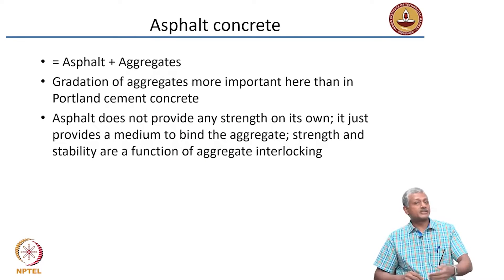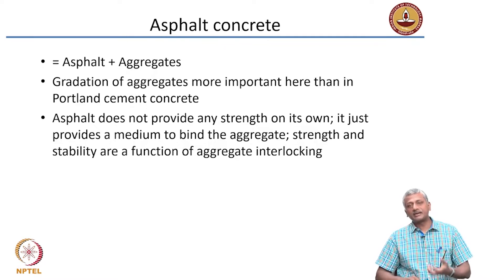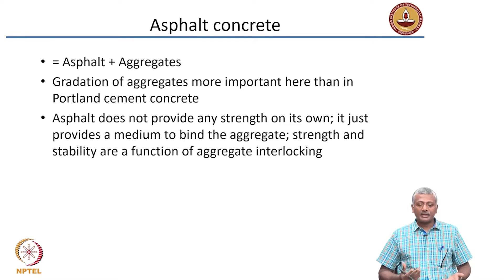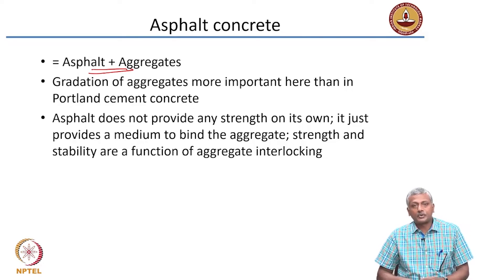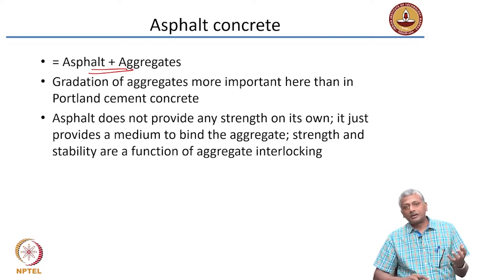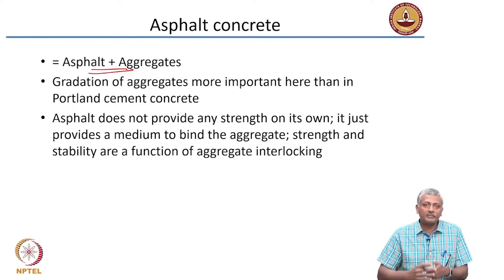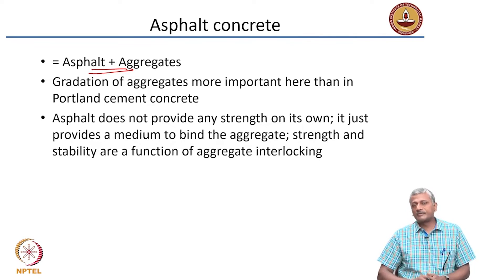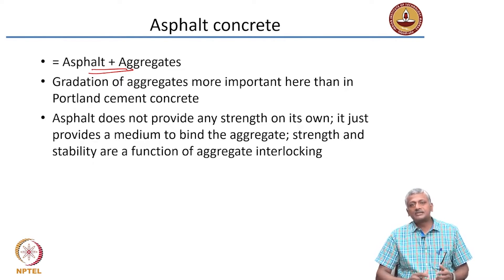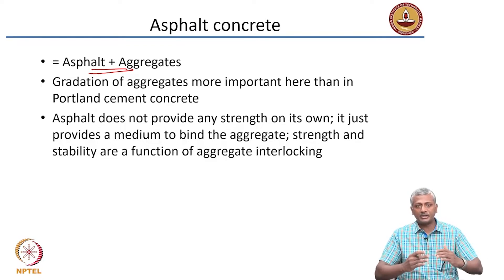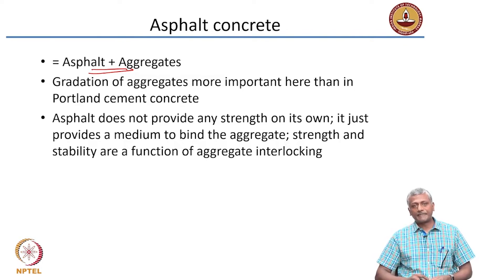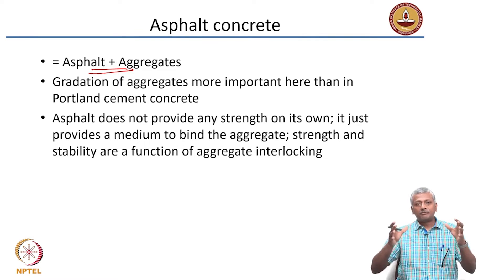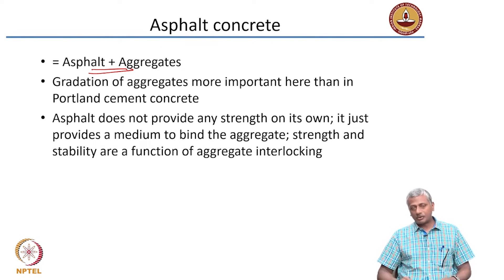Asphalt is not used on its own, just as we do not use cement on its own. It is mixed with aggregate to give a good volumetric material, which we call asphalt concrete or bituminous concrete. In cement concrete, cement hydrates by reacting with water. Not so with asphalt concrete — asphalt does not react with anything. It simply coats the surface of the aggregate, and as it becomes more viscous with the reduction in temperature, it makes a hard solid structure.